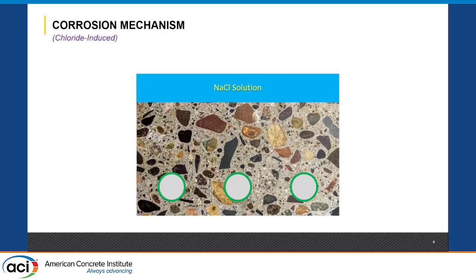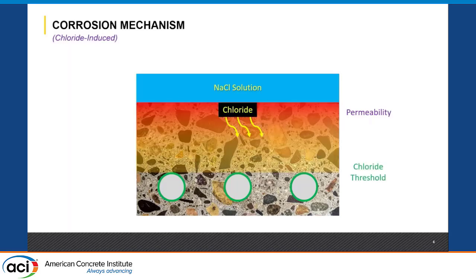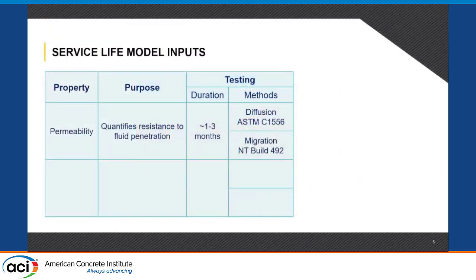You have an exposure to the sodium chloride solution, seawater, de-icing salts, and then the chlorides from that solution are penetrating into your concrete. The rate at which they ingress is based on your permeability. Eventually, you get enough of them in there, your steel reaches a threshold, a limit at which corrosion initiates. Rust products, which are expansive, create an inside pressure, create cracks, and so on. So we don't want that.